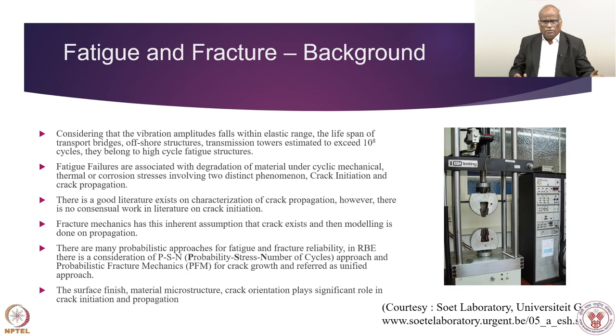So let us see here how the fatigue testing is done. It is a universal testing machine, and the samples are put here, and tests are performed for a number of cycles that has been determined systematically by parametric studies. We keep the amplitude and stress level, and the testing could reach up to 10 to the power 8 cycles for the sample we are putting in here. Fatigue failures are basically associated with degradation of material under cyclic mechanical, thermal, or corrosive stresses, involving two distinct phenomena, crack initiation and crack propagation, that we have seen in the previous slide.